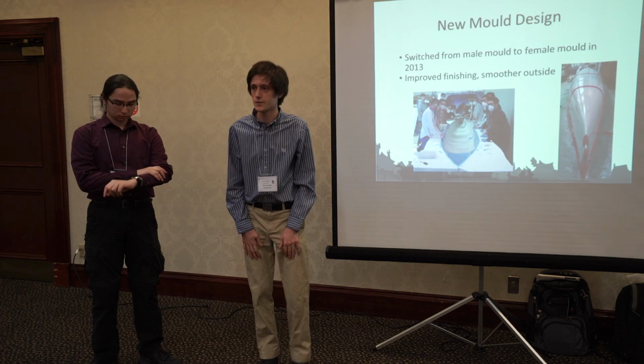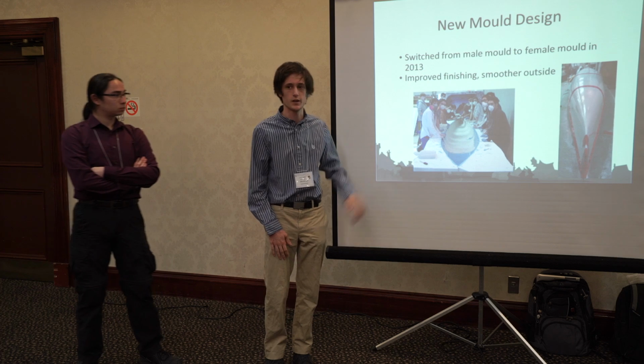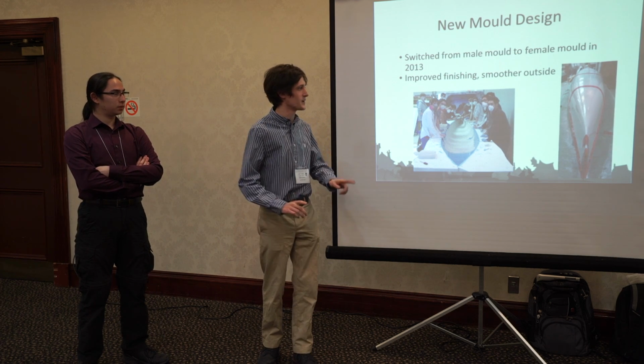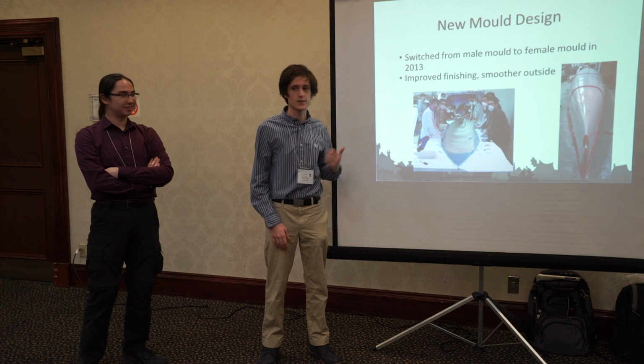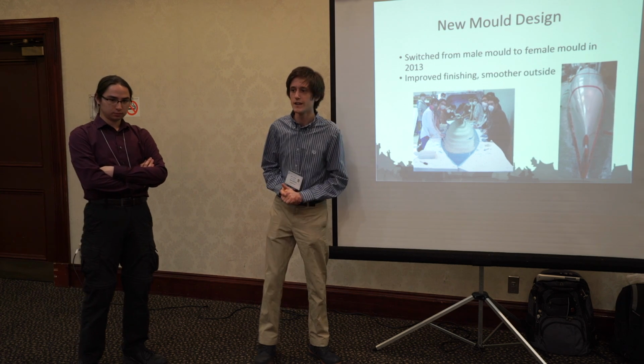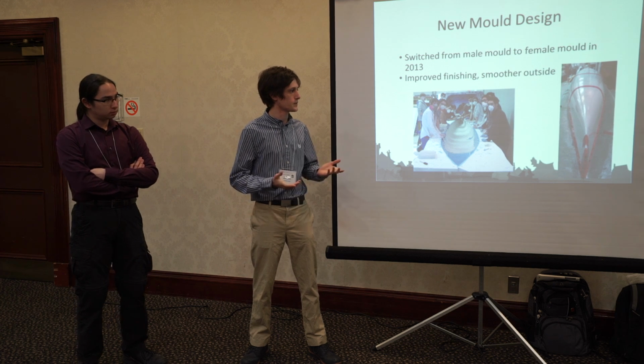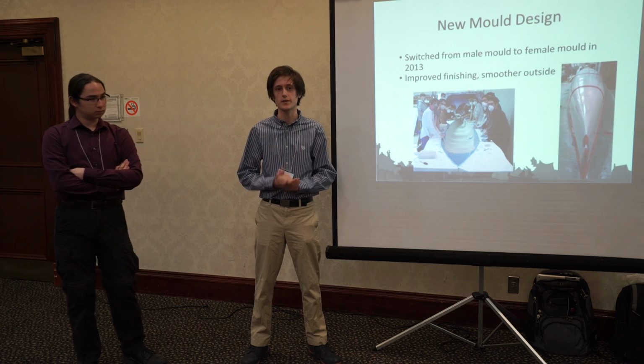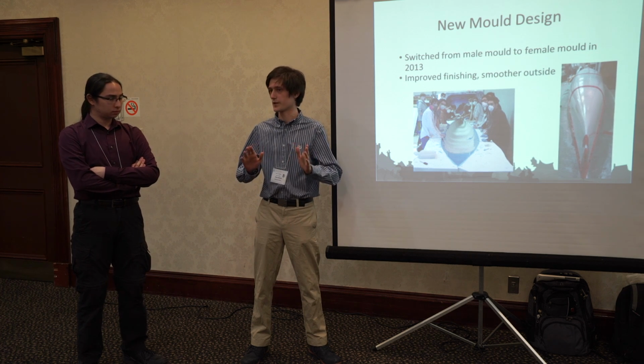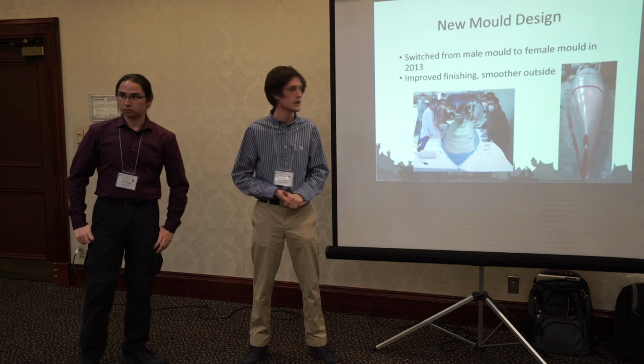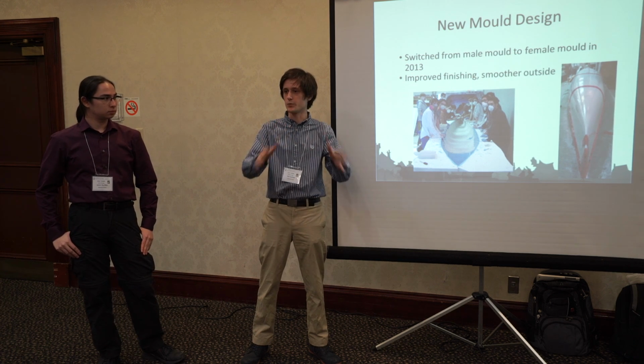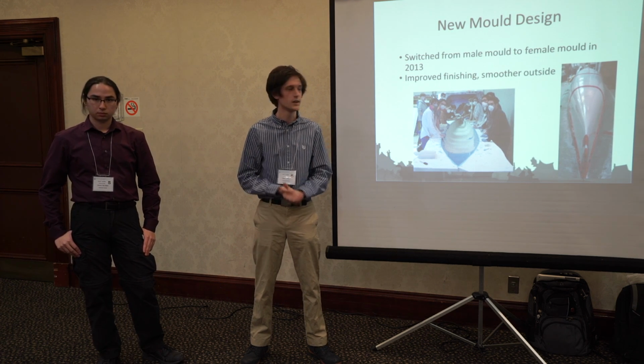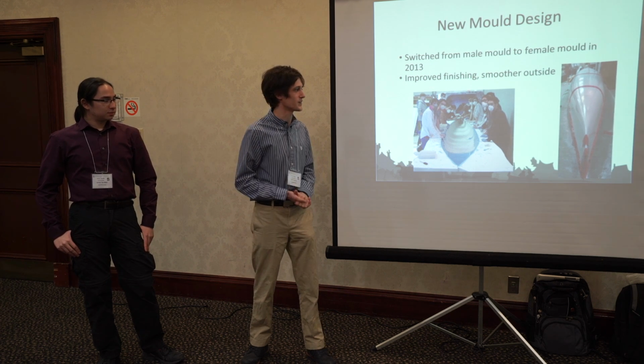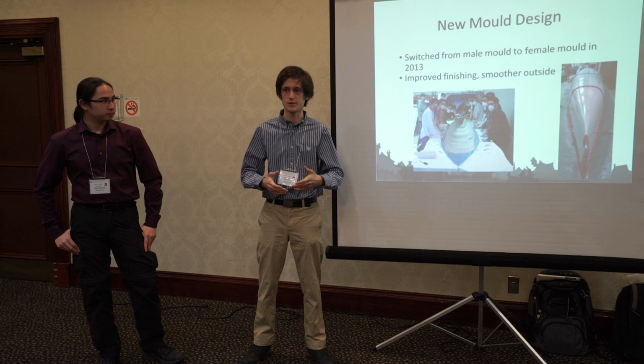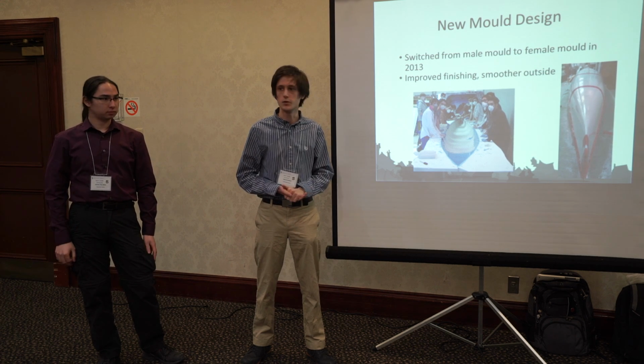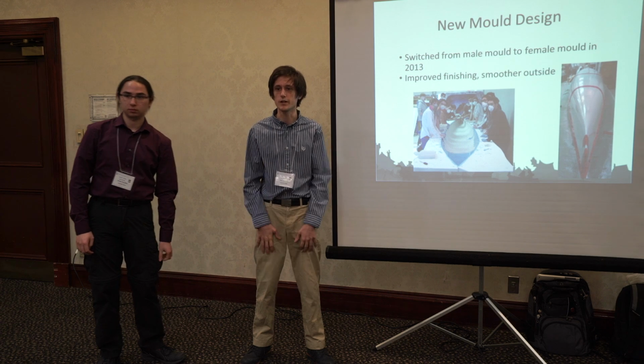On top of that, recently we switched from a male mold to a female mold. This was back in 2013 with the Jinkies canoe, and the reason behind this is we found that with the male mold, because we hand cut the concrete onto the mold, we had a lot of problems with leaving fingerprints and uneven finish on the top of the canoe, as well as a problem of the concrete setting and pulling down the side, which made the gunnel thicker at the bottom of the canoe. So switching to the female mold also made it easier to remove the canoe from the mold without destroying everything, so we can easily just pull it apart.